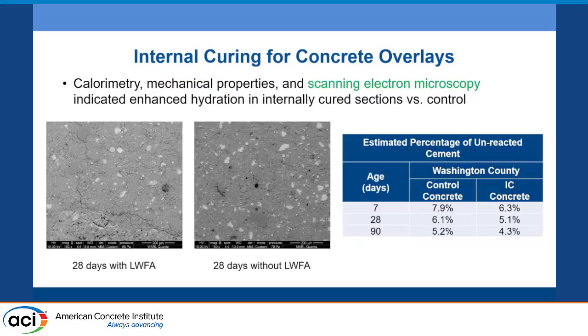And then finally they did take some samples, look at them under the scanning electron microscope, and noticed that it appeared that there were fewer unreacted cement particles still remaining. They did tests at 7 days, 28 days, and 90 days, and at each step in the process, it looks like the sections with the lightweight fine aggregate were all able to achieve greater amounts of hydration than sections without. So in general, a lot of these benefits or properties of using lightweight fine aggregate that we've seen cited, we've seen evidence of in these sections when we look at them compared to the control.